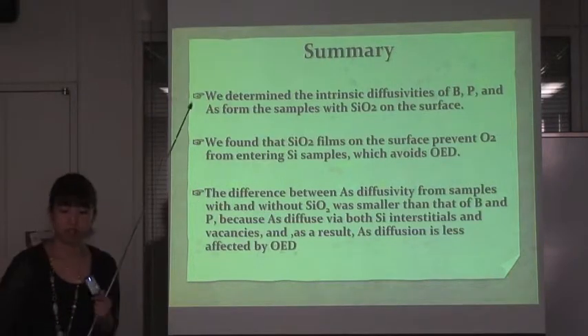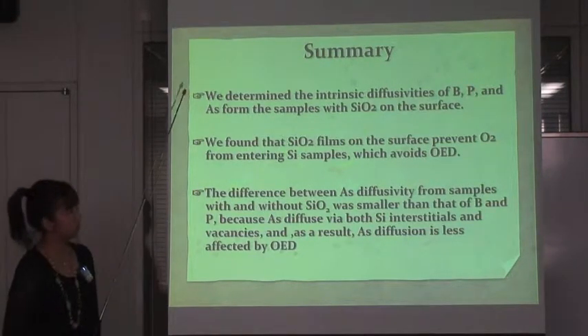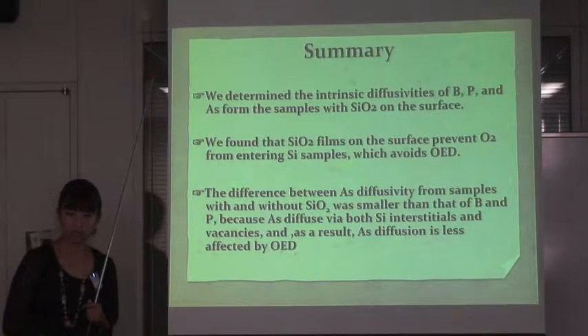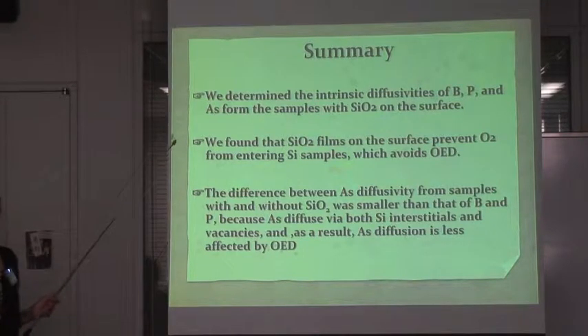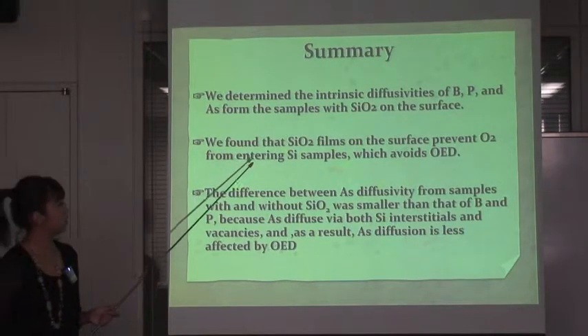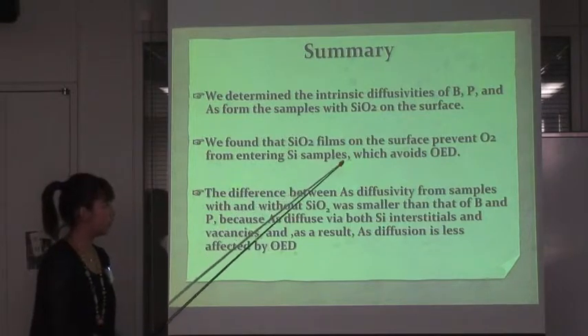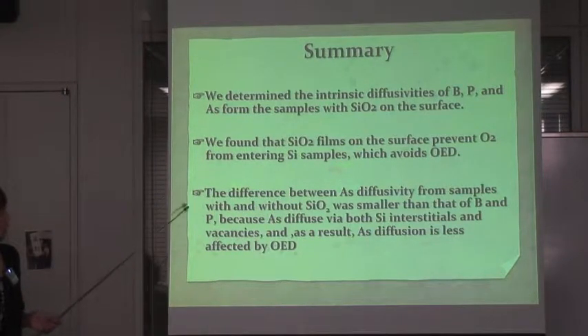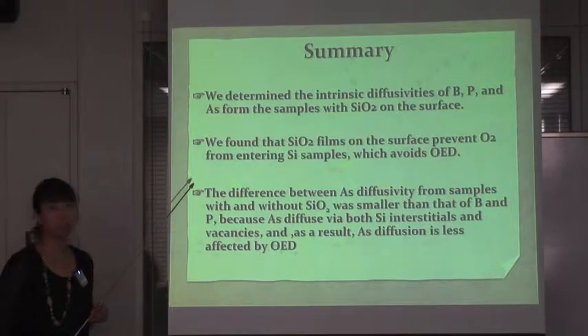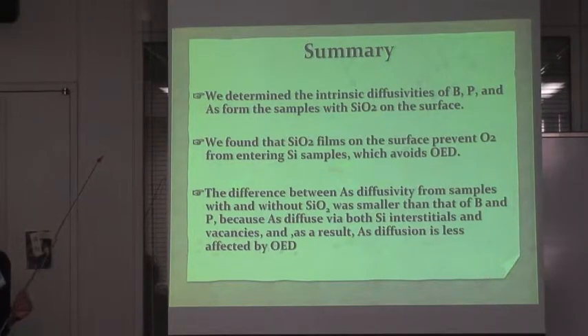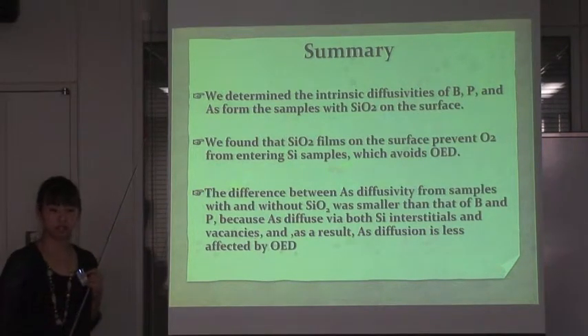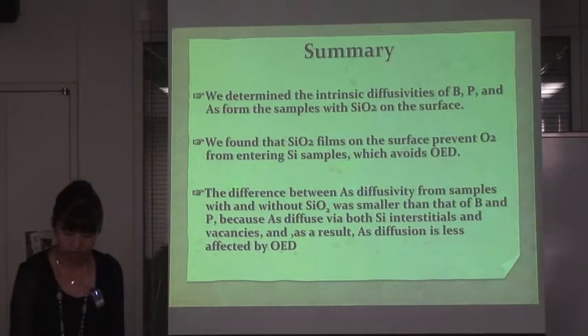Let me summarize my talk. We determined intrinsic diffusivities of boron, phosphorus, and arsenic from the samples with silicon dioxide on the surface. And we found that silicon dioxide films on the surface prevent oxygen from entering the silicon and silicon dioxide interface, which avoids oxidation-enhanced diffusion. And the difference between arsenic diffusivities from the samples with and without silicon dioxide was smaller than that of boron and phosphorus, because arsenic diffuses by means of both silicon interstitials and vacancies, and as a result, arsenic diffusion is less affected by oxidation-enhanced diffusion. Thank you for listening.